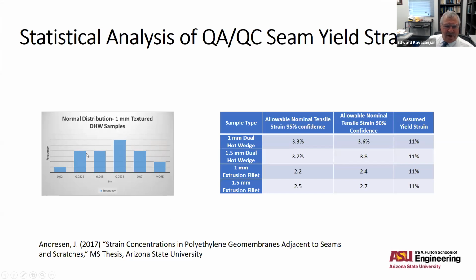And so we used the parameters of that normal distribution to evaluate some confidence intervals for an assumed yield strain of 11%. What would the average strain have to be such that the strain in the geomembrane seam was below the yield strain? Basically, for 90% confidence, the maximum tensile strain was 3.6% in one case with the fusion weld, 3.6, 3.8, 2.4, 2.7 with the extrusion weld. At 95% confidence, a little bit less: 3.3, 3.7%, 2.2, 2.5%. Now, typically we say that the maximum allowable tensile strain in the geomembrane is 4%. But this argues that that limit should be even less.